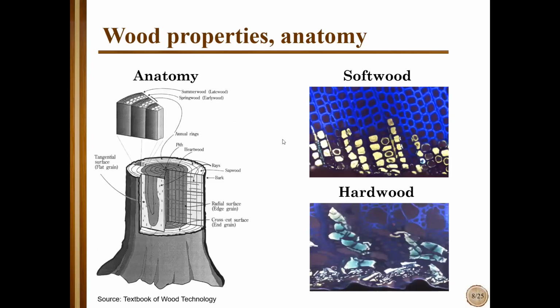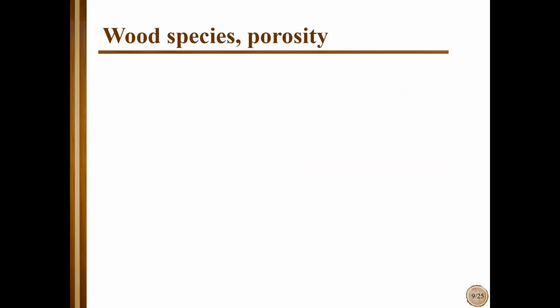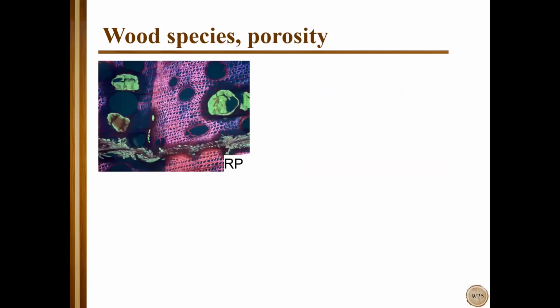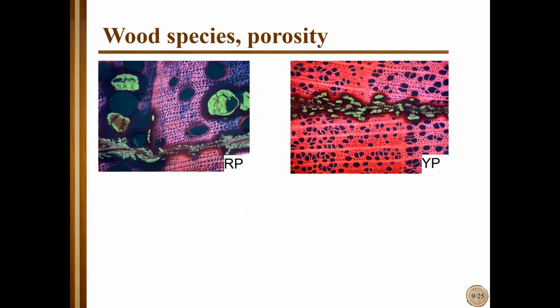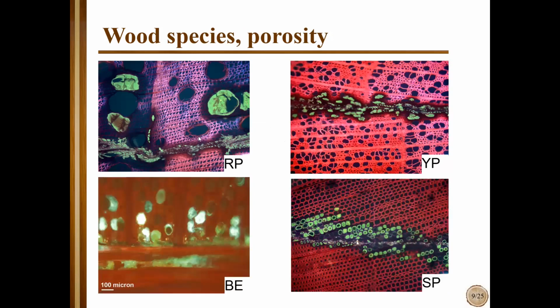Then wood anatomy has important influence on adhesive penetration. So which direction, and also whether we have a softwood or hardwood, then latewood, earlywood has impact, and so on. Some species with different wood anatomy and with different porosity and density. First one is Royal Paulownia, very low density, about 200 or a little bit more kilograms per cubic meter. Yellow poplar, 350 to 400 kilograms per cubic meter. Or beech, Fagus sylvatica, almost 700 kilograms per cubic meter, and southern pine about 500. So different porosity, different density, different anatomy or structure also impacts the adhesive penetration and distribution.